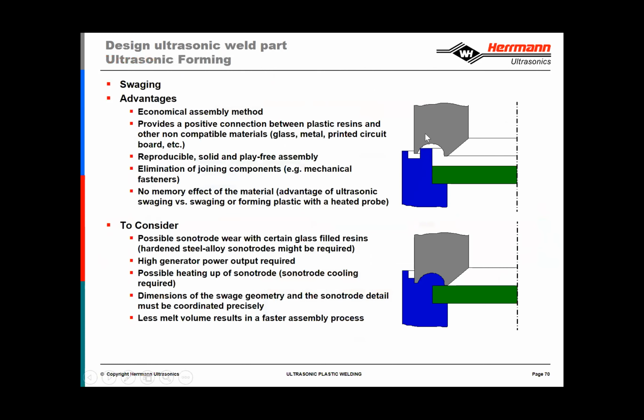We can use steel sonotrodes. We can use a coating on the sonotrode, but the melt volume calculation is quite critical in this case.